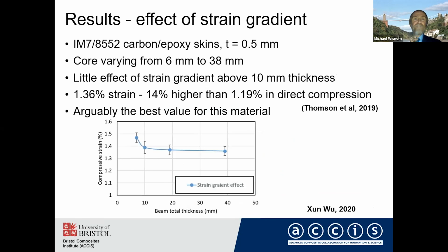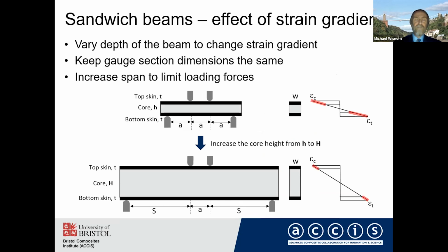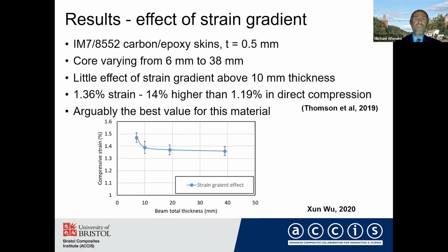If you look at the results for that, this is for IM7/8552, where the skins are 0.5 millimeter thick. This is the slide here. Let me just show you what we've done to vary the strain gradient. The depth of the beam can be changed independently. When we change the depth of the beam, we can keep the distance between the rollers and the width the same, so the volume of material is the same, but we've got a different strain gradient. We also have to increase the span in order to limit the loading forces and prevent a localized failure. By doing that, we can test with the same volume of material and look at the effect of that strain gradient.